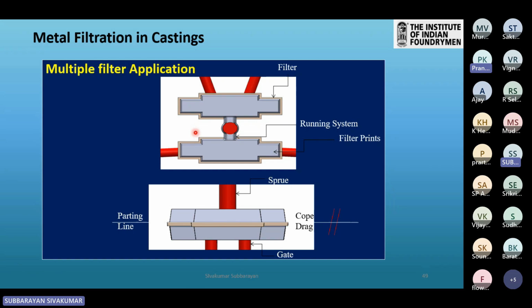I can say it is a hybrid solution for bigger size castings, and we came out of the issue of filter breakage in a big way. After we implemented this, that filter breakage issue is totally eliminated. Once the filter breaks, again the casting is gone. Already we are spending 1 rupee, 1.5 rupee per kg of casting for introduction of filters. Because of spending more, if you are losing casting, it is purely lack of proper engineering knowledge. Once we think with multiple options like this, we can find a solution to avoid any filter breakage.